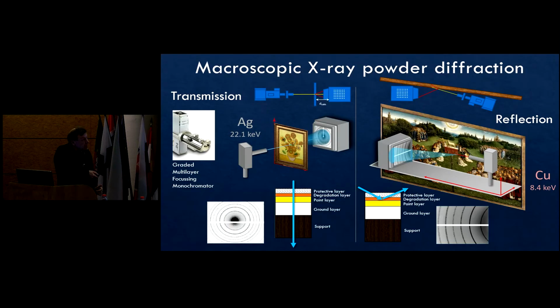All right. So this macroscopic X-ray powder diffraction we can use in transmission mode. That's relatively easy. We put an X-ray tube in front and a detector in the back. And as X-ray tube, we just don't use the entire beam. We have a monochromator that's also focusing, so that we have about 100 microns here, which is very big in synchrotron terms, but the right size for meter-sized objects. And so then we sample with XRD all the layers that the beam is going through.